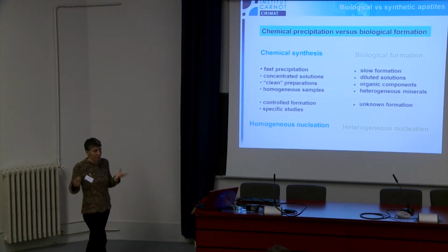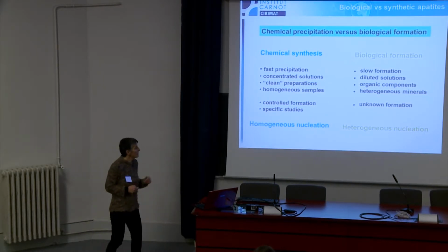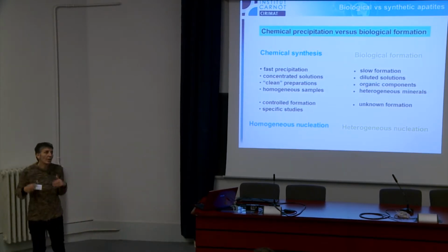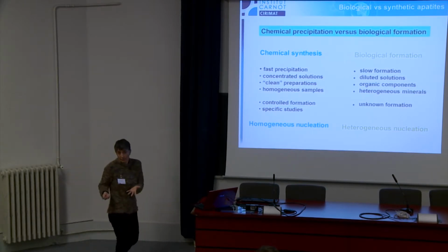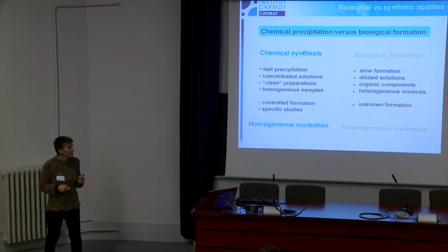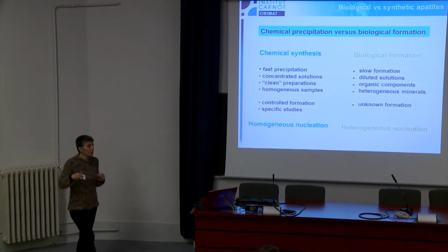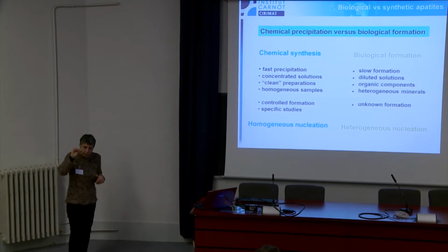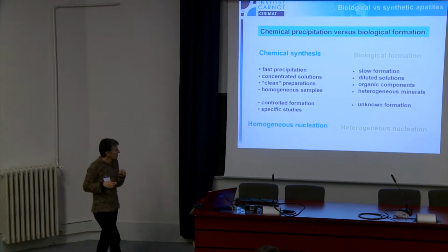The solutions are more dilute than in chemical synthesis. We also have the presence of many organic components that can act during this formation, and the formation is mainly based on heterogeneous nucleation. I told you that it is now well accepted that the first crystals are formed within the holes between the collagen fibrils.